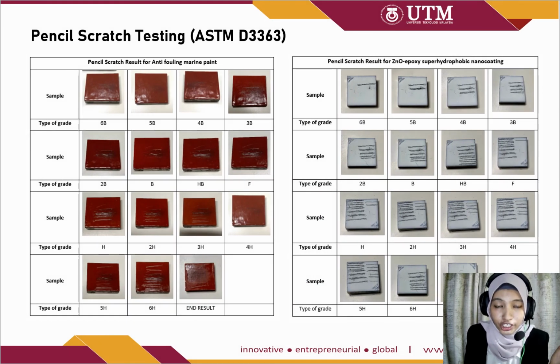Next, on the abrasion test, I did a pencil scratch testing with ASTM D3363, where the zinc oxide epoxy nanocoating shows no abrasive wear on the surface, even after being cleaned. I'm sorry, but the marine paint surface shows some scratches.